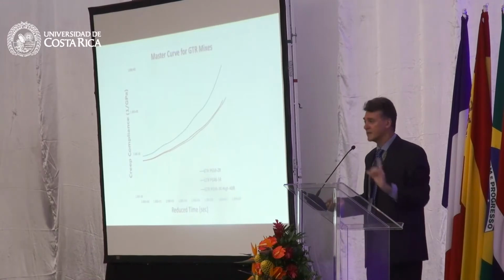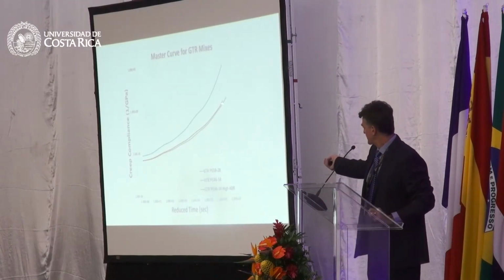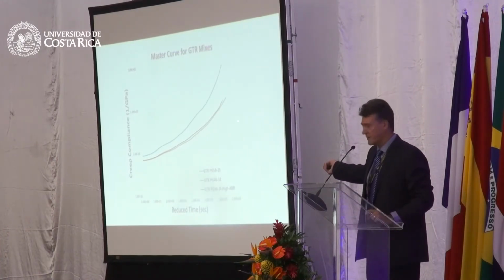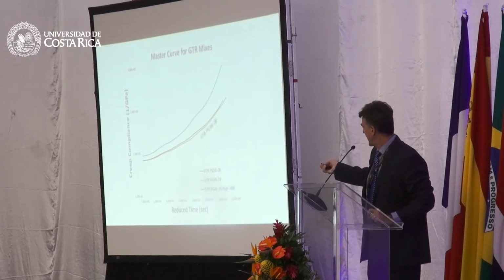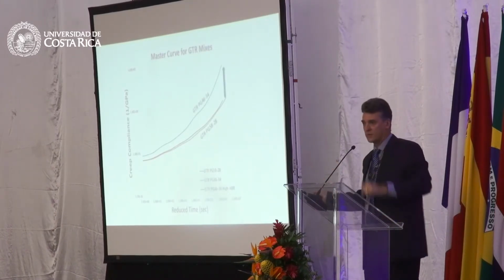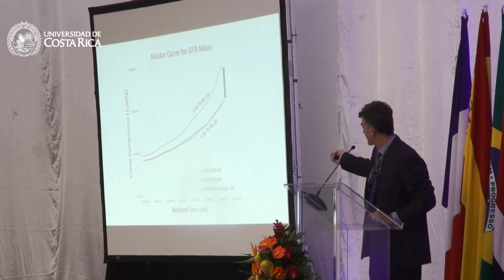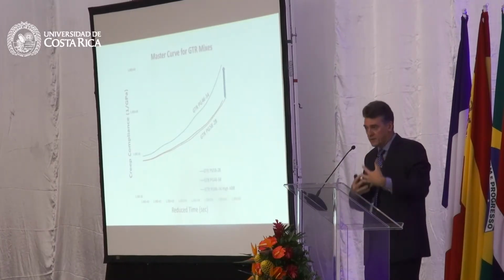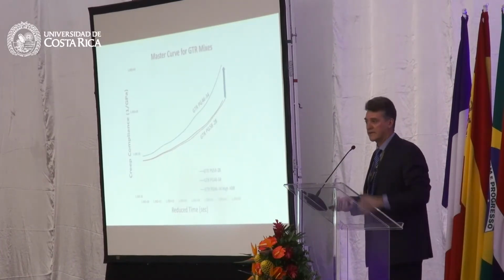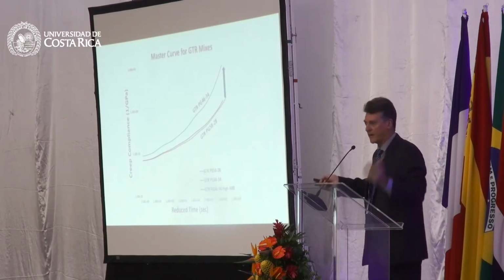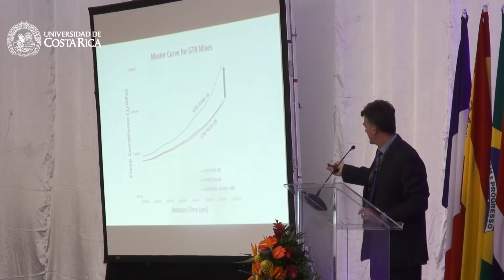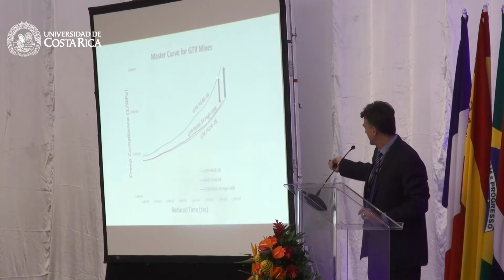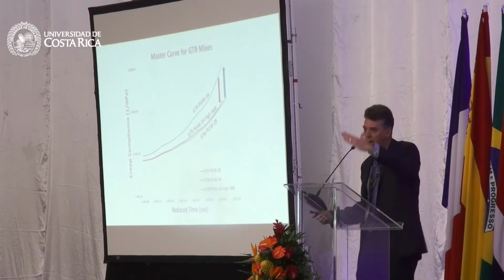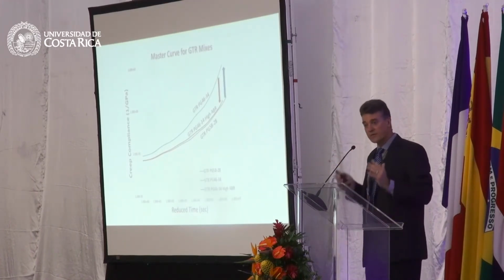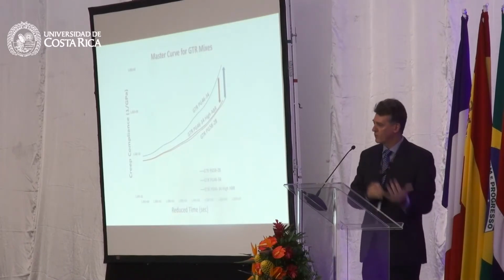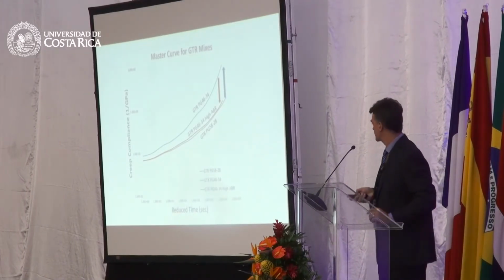Sure enough, we saw the exact same trend, where the -58 binder was in the bottom set. As we add the -34, or substitute to -34, the creep, the ability to relax stress is improved. It's just like getting a better bending beam M value or a lower stiffness. But then when you add the higher recycling level, into 47% recycling, you go back towards the control mixture. So the thing that we saw for fracture energy, we also saw for creep compliance.